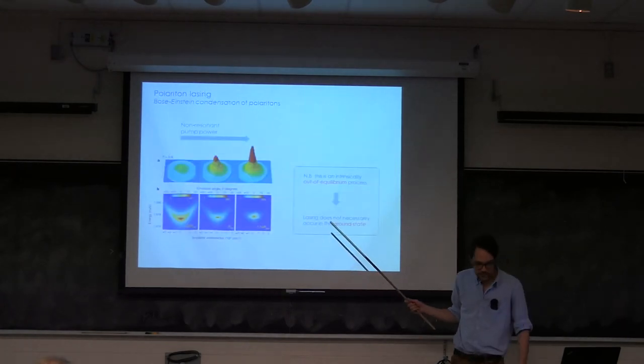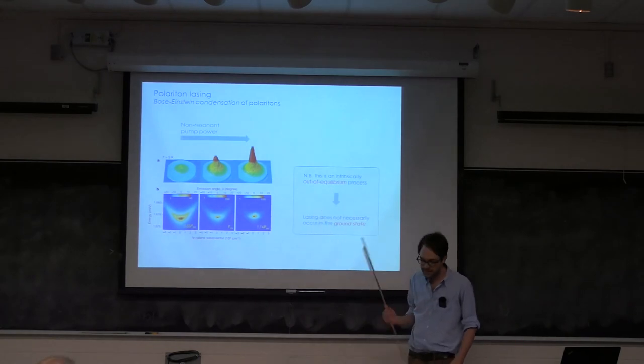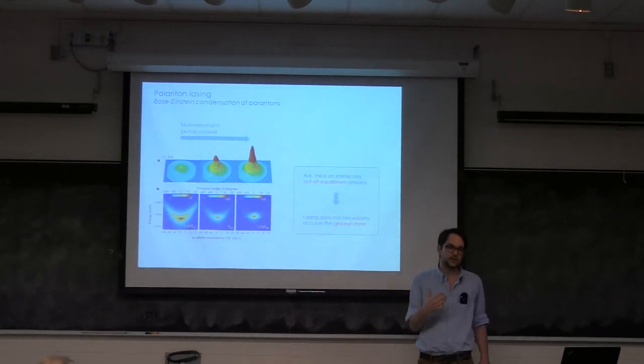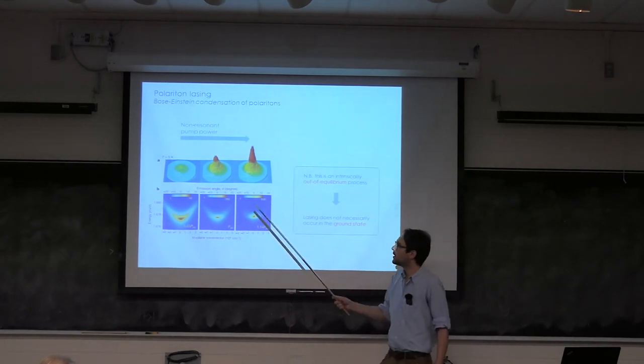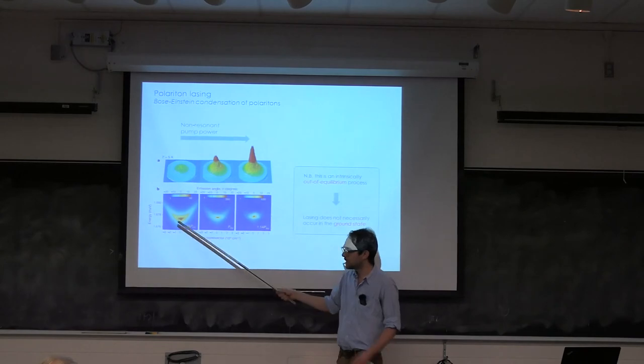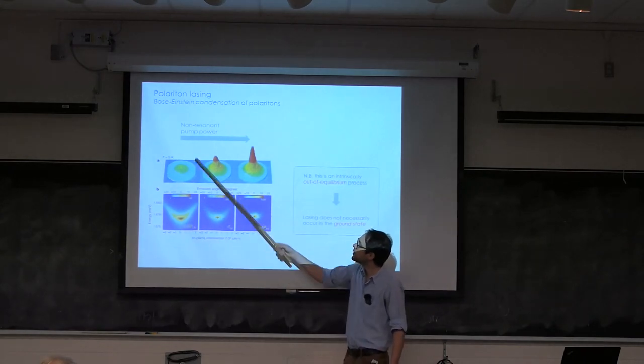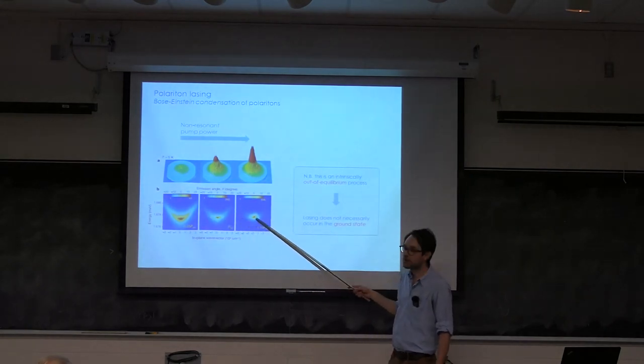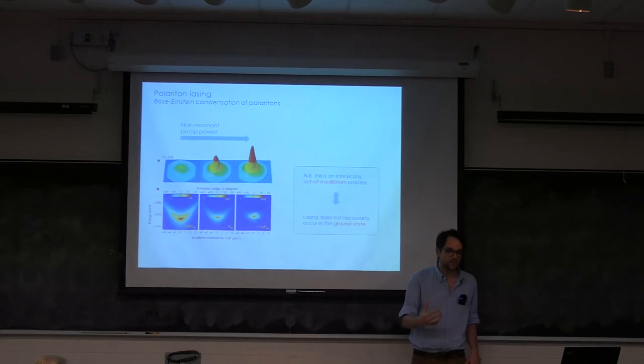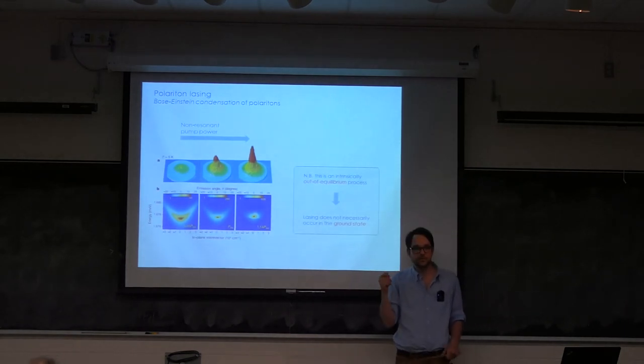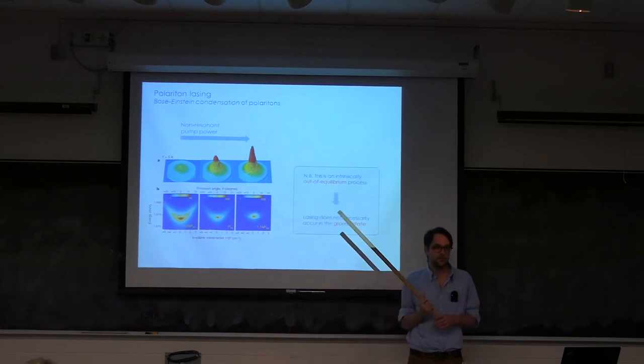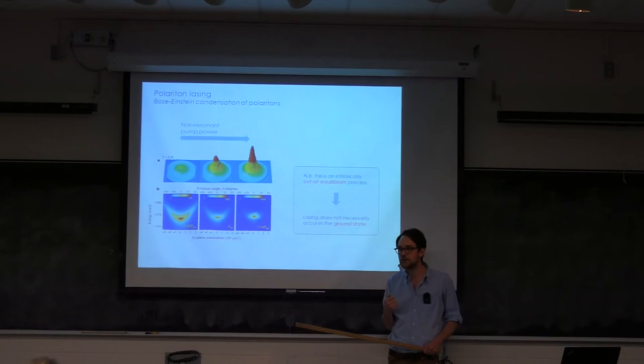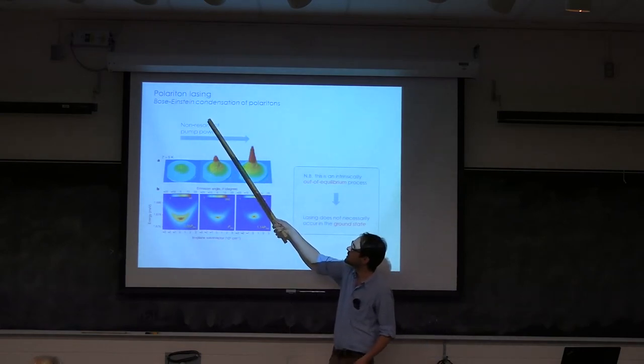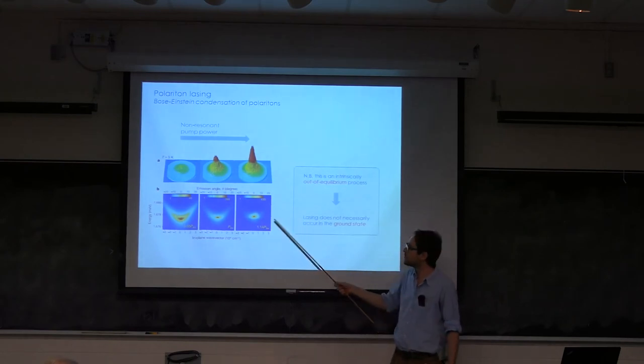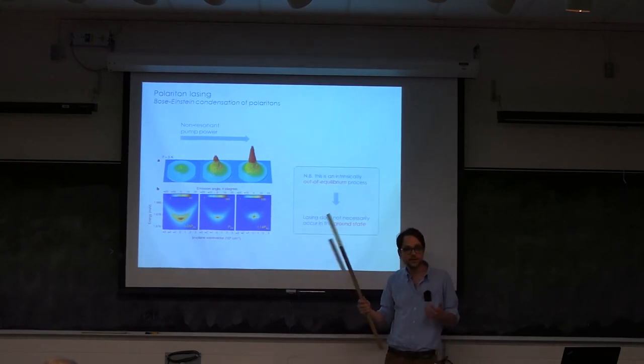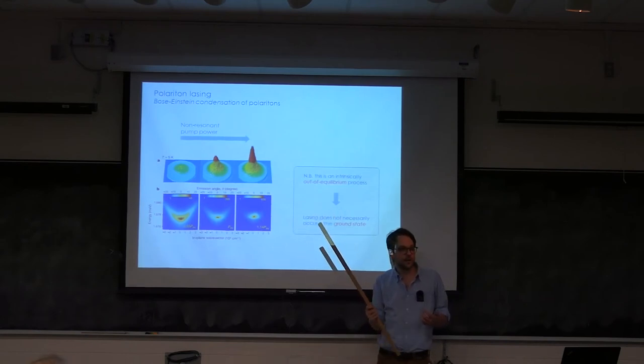And for this latter point, in fact, these polaritons are well known to lead to a phenomenon that was historically called Bose-Einstein condensation for polaritons. So if you have a low excitation power, again, this non-resonant excitation, you start to populate your whole band, you increase the pump power, and you start to have a massive occupation of a single state. So people were calling this Bose-Einstein condensation. This is something that you need to take with tweezers because we really have an out-of-equilibrium system. There's a really strong dissipation, and there's a strong drive also. So rather, I usually prefer to call it polariton lasing, which is different from a usual laser because our eigenmodes are still in the strong coupling regime. So we have a fluid that is coherent, highly coherent, but also strongly interacting.